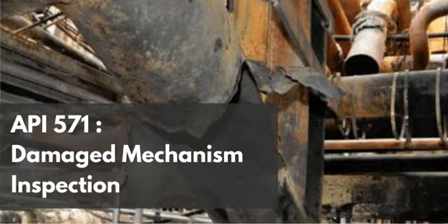Right. The magnetic flux leakage or the induced eddy currents simply cannot bridge the gap created by thick, non-conductive, non-magnetic scale. The particles won't gather, or the probe liftoff will be too high to read the impedance changes. So the text strictly mandates that the surface must be aggressively cleaned. It does. And it doesn't just say clean it, it provides the specific, authorized mechanical methods: grit blasting, high-pressure water blasting, or flapper wheel abrasive grinding.